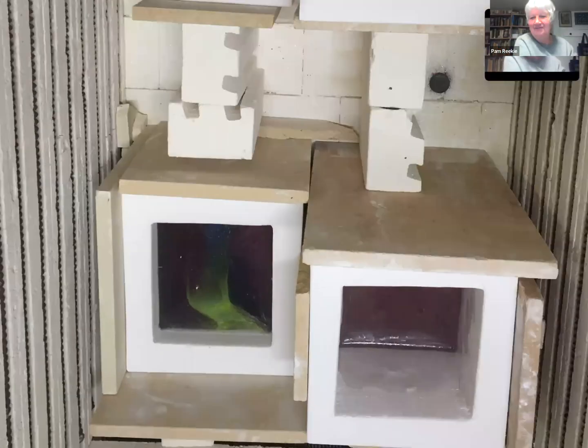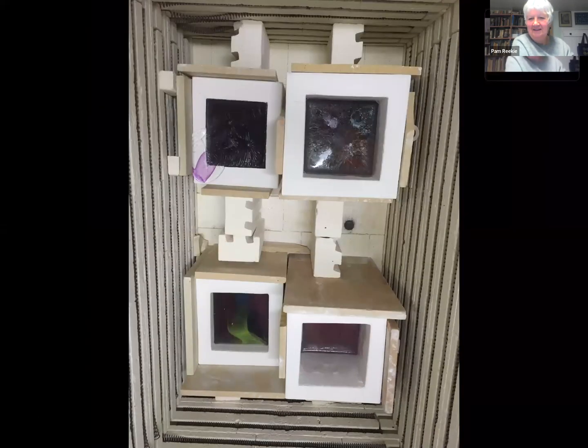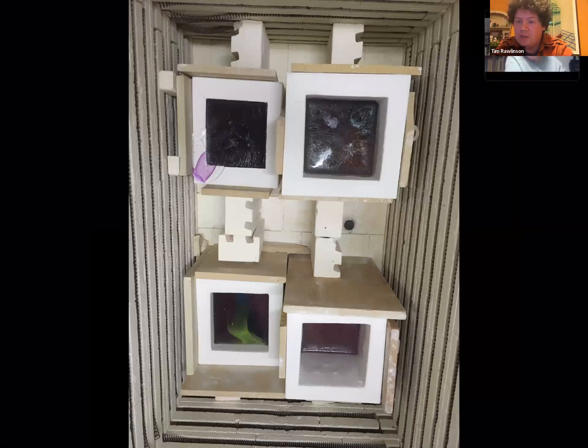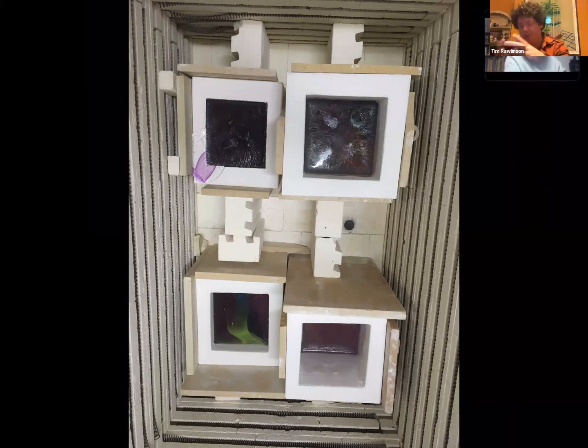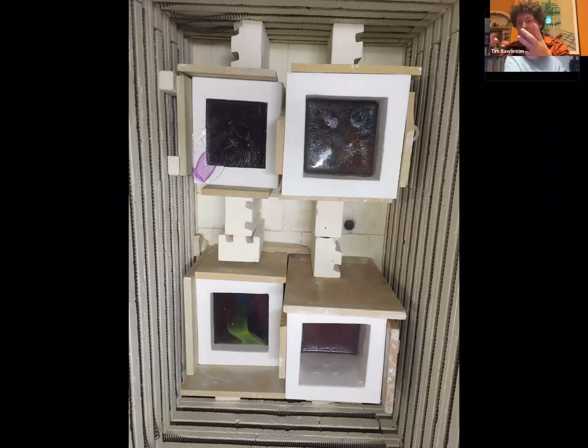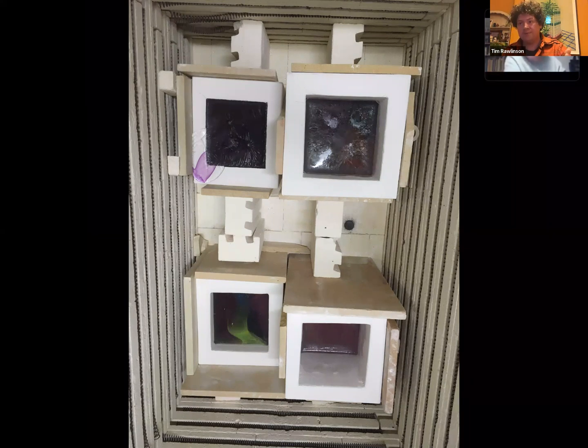How many hours have you got them in the kiln for that? Well, like I say, something like these cube pieces, the annealing is a month. Right, so you're holding them at a certain temperature. Yeah, so you very slowly heat the glass up, especially because it's a blown glass form, so it's already got the size. It's not necessarily individual billets. So you slowly heat it up or the glass will crack.